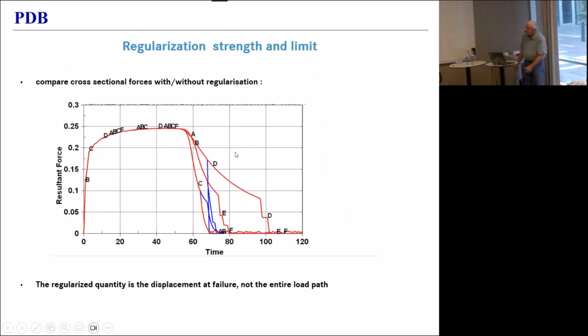If you put that in a graph in terms of force displacement, you see what happens here. The red curves are without regularization, so the coarse meshes fail later. The blue curves are with regularization, and we manage to make them fail all at the same value of the displacement. Now that graph shows you the power and the limitation of regularization.